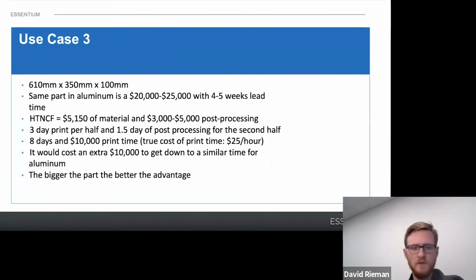And next slide. So as I mentioned, that duct mold was about 610 millimeters by 350 by 100. A similarly sized part in aluminum would probably be about $20,000 to $25,000 with 4 to 5 weeks of lead time. Because this part was imagined as being like a polypropylene duct, we went with that HTNCF. The amount of material was roughly 12 kilograms after the final slicing, and that's just because, again, it has that 6 millimeter shell all the way around it, those 20 top layers, those 20 bottom layers, and the 8 perimeters for the part, as well as those fully solid crash pads on all the corners and in the middle to help evenly distribute weight off of that pinch point.